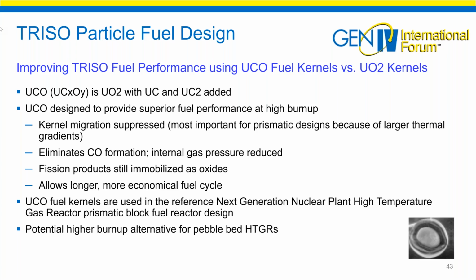The CO pressure, the carbon monoxide pressure, is higher. And in the UO2 design, you'll actually see pyrolytic carbon fractures occurring. And you'll see oxide formations, like cesium and palladium oxides, that attack the layers. So we've gone through this with the AGR-1 and 2 PIEs, where we looked at the different mechanisms and postulated what was causing them. And there's a document listed in the program plan where we actually do that.